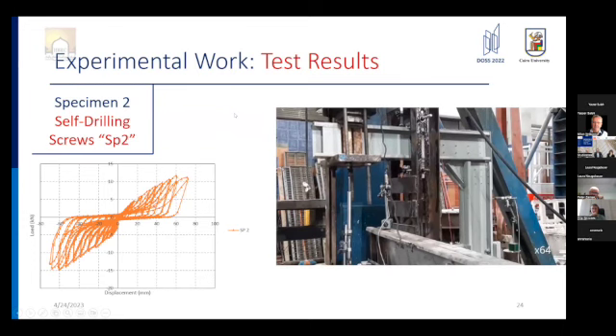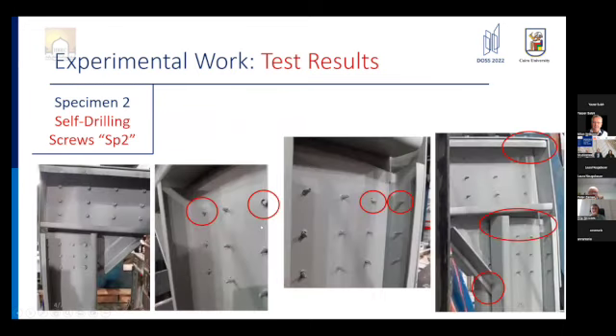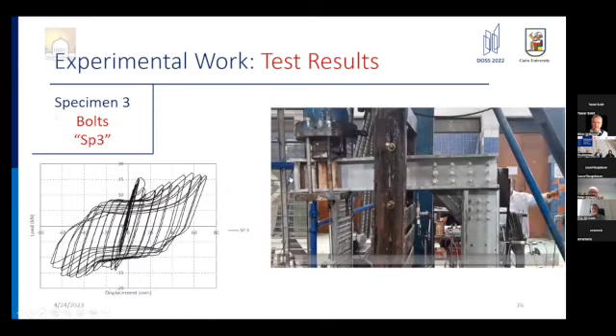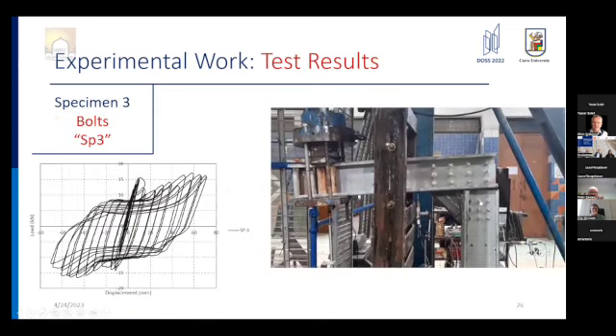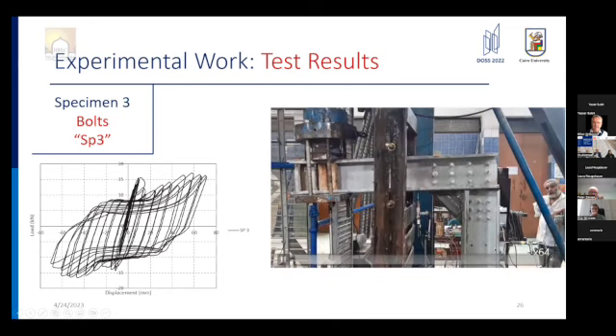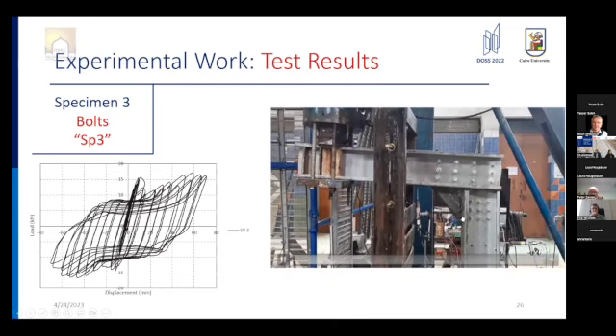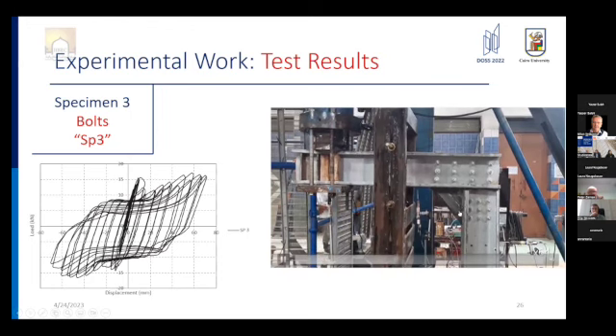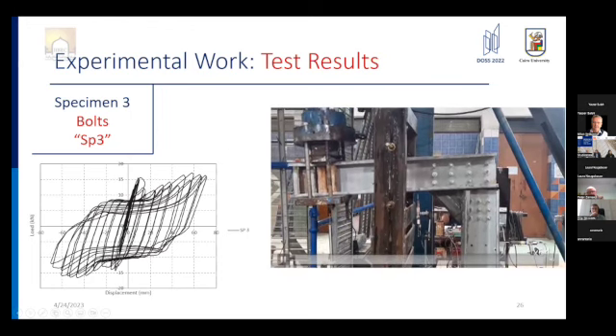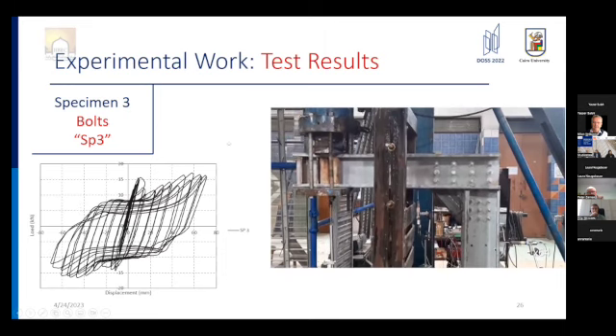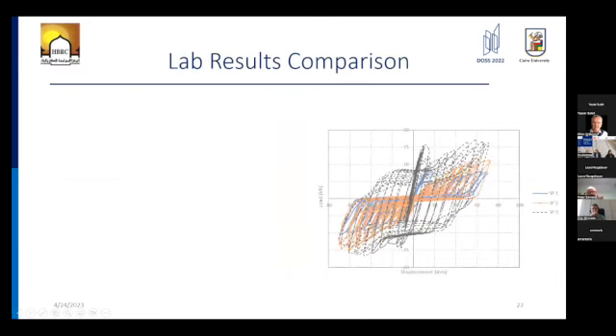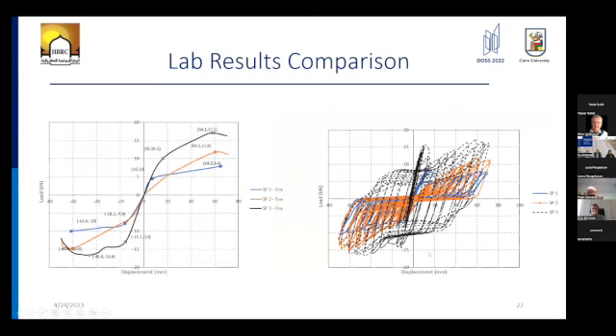This is the second specimen. You can also notice here tilting of the screws in addition to minor deformations in the steel sections. This is the third specimen with a different failure mode or deformed shape, where buckling of the gusset plate followed by buckling of the column section was noticed. Also, the shape of the hysteresis loops differs. You can see it better here. We can compare the shape of the curves subjected to cyclic loading and see the difference in the behavior of the different connections.